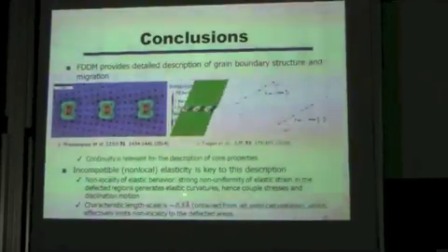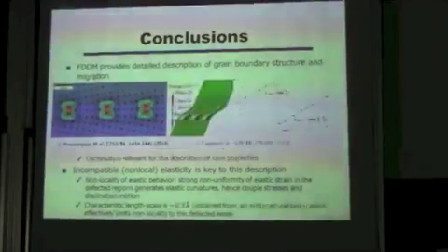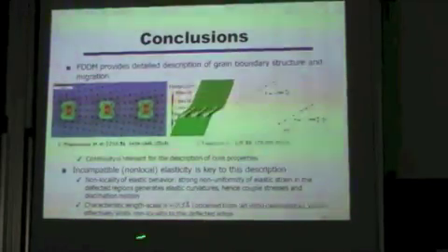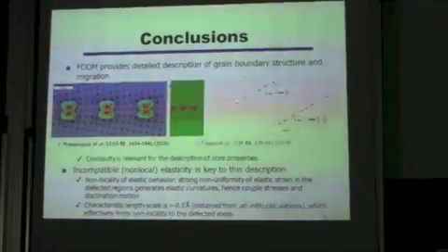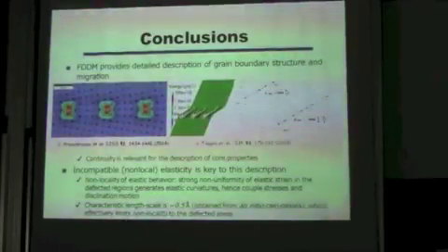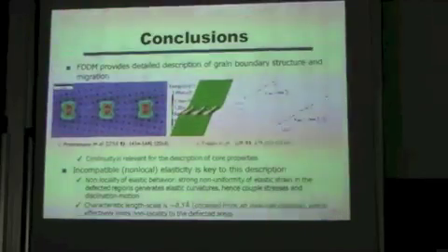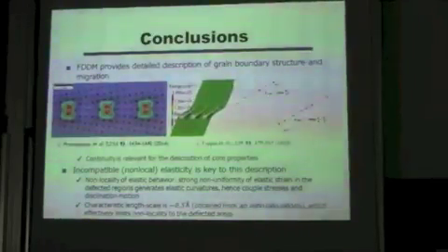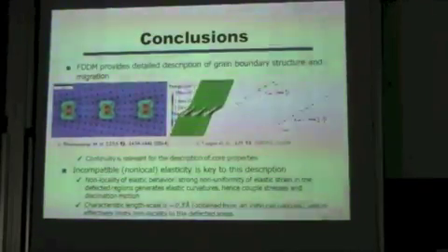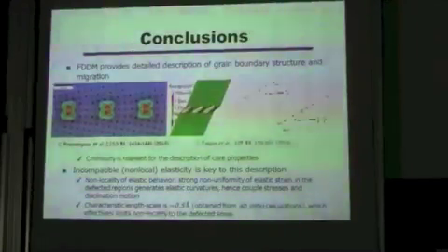Third point, I want to stress this one. The characteristic length scale is 0.5 angstrom, which is very small. You cannot see it here, but there is a reference to a paper by Maranganti and Sharma in JMPS 2007, where they obtained this length scale from DFT ab initio calculations. So we just borrowed these results. They perfectly fit with what we do because they effectively restrict the non-locality to the grain boundary itself.